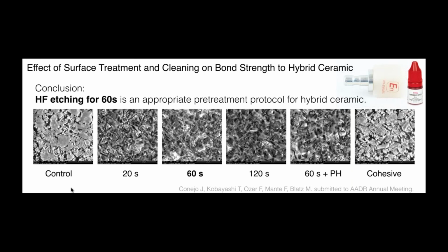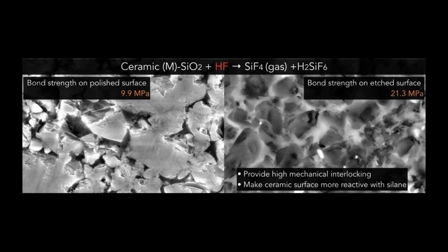The good thing is that in these in vitro studies we did, we have cohesive failures, meaning that we can bond very well. So etch for 1 minute, apply a silane coupling agent, exactly the same as we do for feldspathic ceramics, but also protect the bond strength to the side of the tooth as we explained.